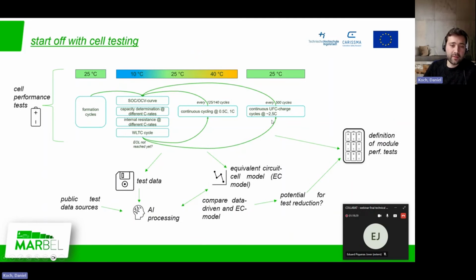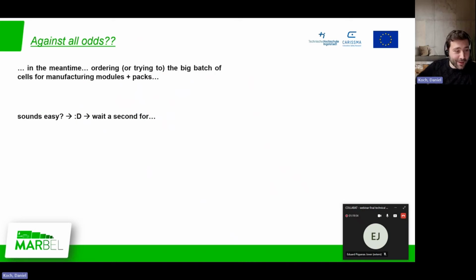One of the results of the ultra-fast charging tests was that the cells aged way faster than we expected, so we had to adapt our ultra-fast charging strategy. The continuous cycles were then replaced, not by the ultra-fast charging from 5 to 80% and down to 5, but with WLTC cycles. Now, you might think it's time to order the second batch of cells at the manufacturers,